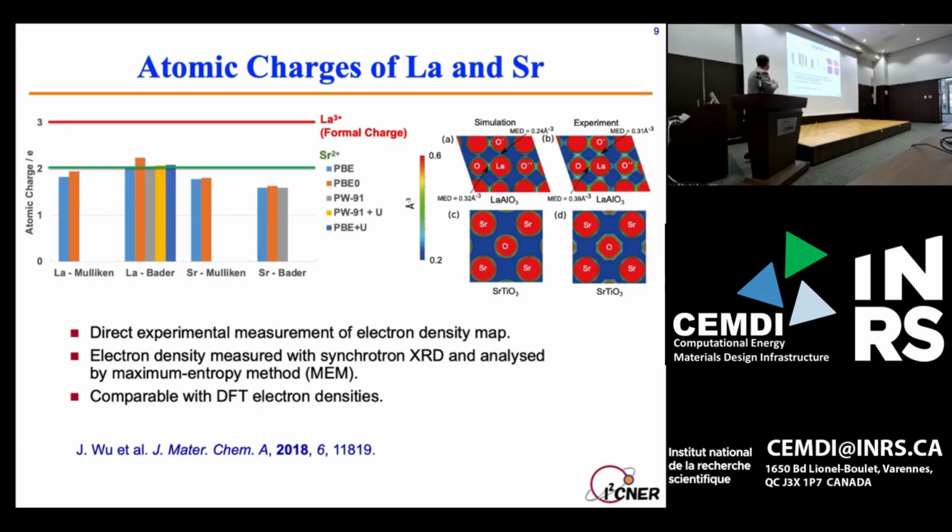We looked where this electron density of lanthanum was, the remaining electron density, and it was actually located at the d electrons. And certainly, as the theory of valency was created, it started with a theory for bonding between the first and seventh group of the elements. And yes, indeed, they are very ionic. However, then it was carried over to the entire periodic system. And the elements between the seventh and the first group, they actually do not really obey those complete charge transfer between cations and anions. You have a lot of residual electron density, or ionizing d orbitals is very different from ionizing s orbitals.